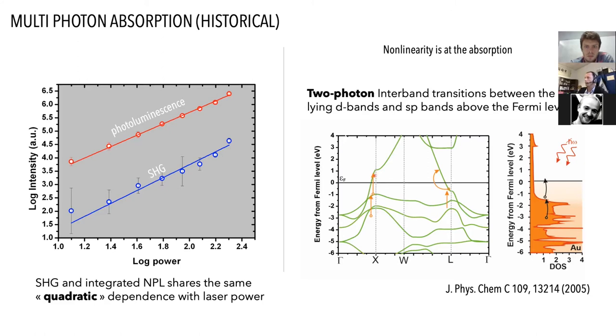and then you will have successive recombination between the hole created in the D band and the electrons in the sp band, and this gives rise to this broadband photoluminescence. Especially around this symmetry point of the Brillouin zone, which is basically the X and the L points, where the band structure will allow these two photon transitions.